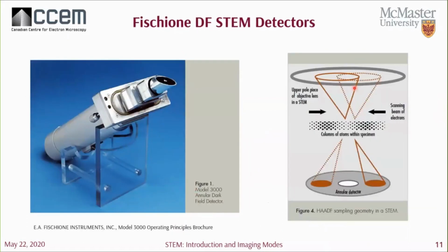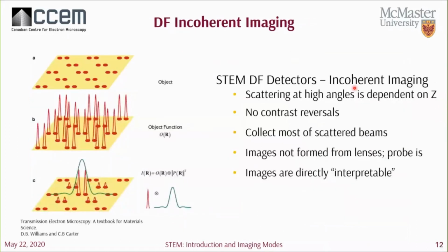So one important advantage of using dark field imaging is that you're collecting these incoherently scattered electrons. So they can be quite useful in a way that it simplifies the interpretation of images that you get, as opposed to say looking at a phase contrast or diffraction contrast image that you get from a TEM.